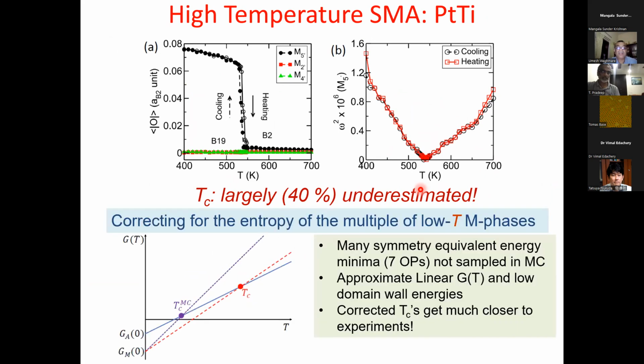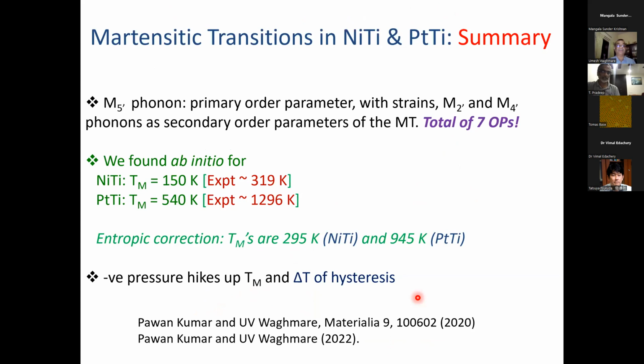So we looked at a way of correcting it, and basically what we did is to include configurational entropy associated with several local minima of the martensitic phase. And using certain approximations, we show that TC actually is much higher than what Monte Carlo simulation gives, and that is much closer to experiments, but still there is underestimation of the transition temperature.